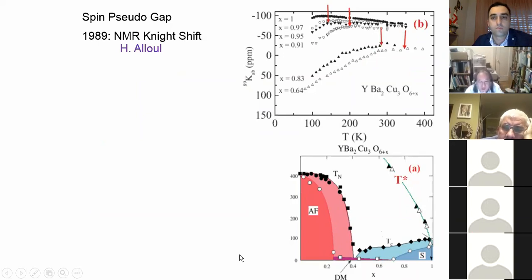So the fourth element that I argued is that there is something called pseudogap behavior, and it is observed again. This is somehow different from a BCS superconductor. So in the cuprate system, this is the phase diagram of the cuprate, and if one measures the Knight shift, the magnetic susceptibility, that shows reduction from very high temperature, not at the superconducting temperature, but from very high temperature. And that is not expected in BCS. In the BCS, you would expect the reduction only in the superconducting state.